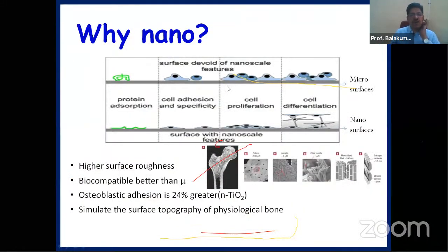So that is one. But what is the help of nano? So far, what we have discussed uses nano form or micro form. When you take protein adsorption with a microform, the cell adhesion, cell proliferation, and cell differentiation are not many. Whereas, as I mentioned earlier, with the nanoscale, this adhesion, proliferation, and differentiation are significantly enhanced if you use the right size with the right surface area, very close to the bone, so that it is biocompatible. Adhesion percentage increased to 24%, stimulating the surface topography of physiological bone, which is a major advantage.